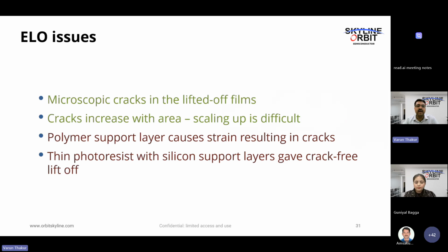So previously, ELO had issues. We used to see these microscopic cracks in the lifted off films, which increase with area. They used polymer support layers, but they also caused strain. Again, there were cracks. But now photoresists with silicon support have given crack-free lift-off. So this was a research problem. This has been resolved.